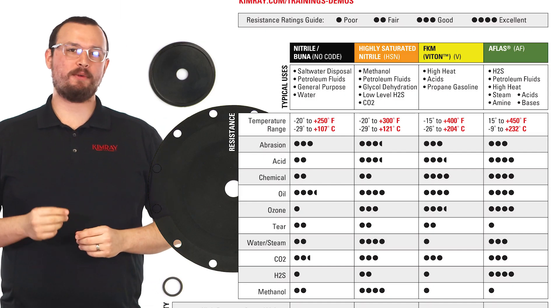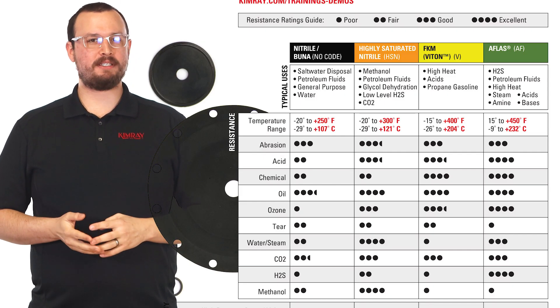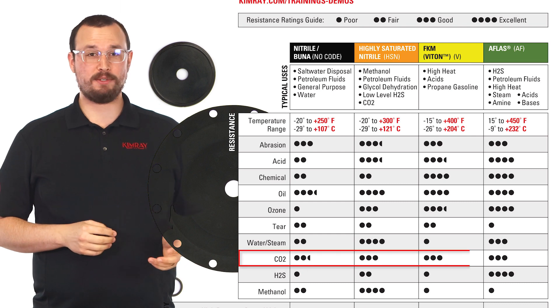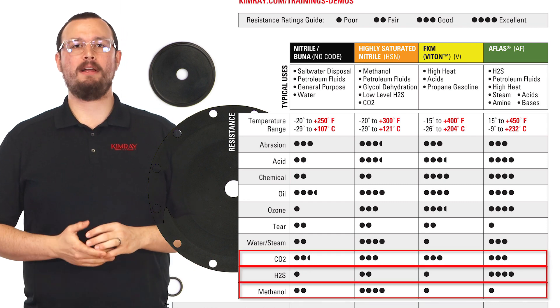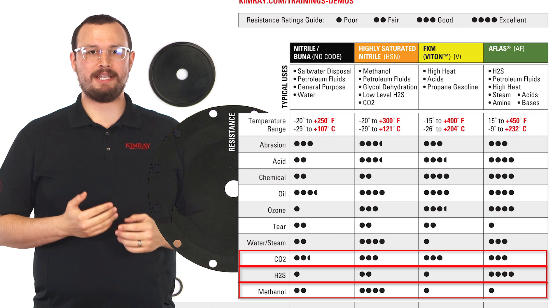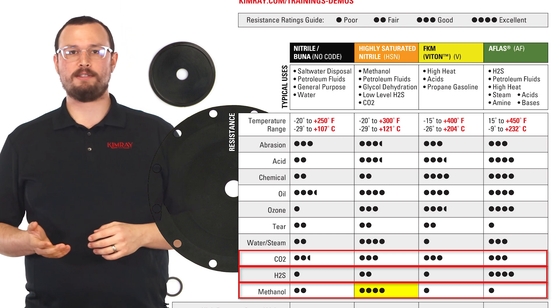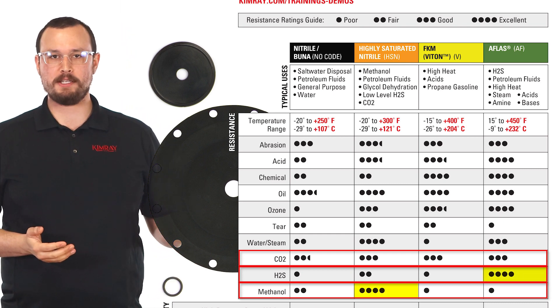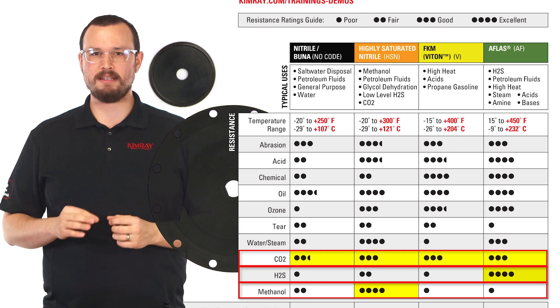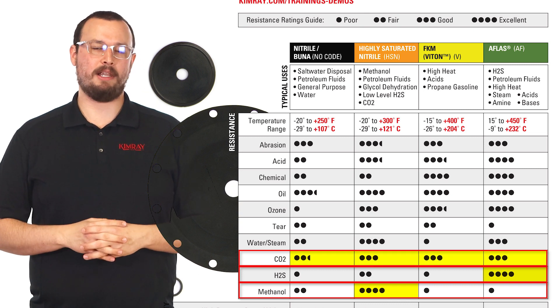When you're dealing with corrosive conditions you'll need to consider important resistance rating categories like CO2, H2S, and methanol. Some are clear, such as using HSN for high levels of methanol or AFLAS for high H2S presence, while others like CO2 have similar resistance across each elastomer.